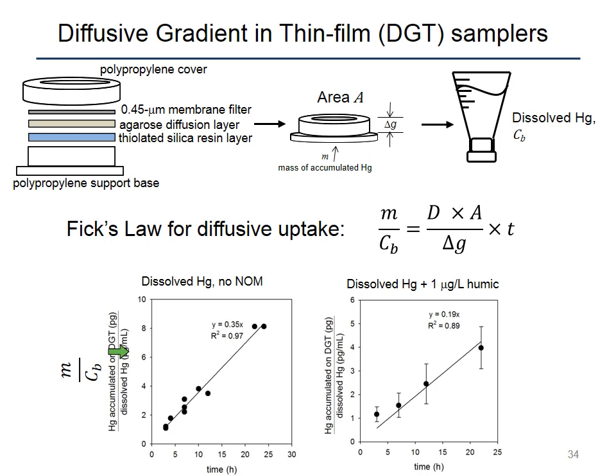Another similar approach that could be taken is using in situ passive samplers, such as diffusive gradient in thin film samplers, also known as DGT samplers. These are also thiol-based samplers for mercury. If you're not familiar with these, you have a plastic housing, and inside this housing you have a thiolated silica resin layer that acts as a sink for dissolved mercury. This resin layer is overlain with an agarose diffusion layer and then a 0.45 micron membrane filter. And it makes a sandwich where this all compresses into this sampler here.